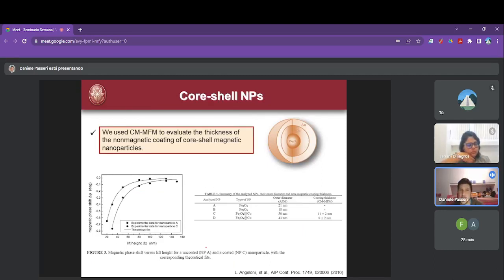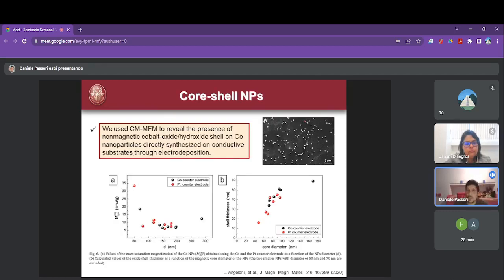Another application: we tried to measure the thickness of the shell of core-shell nanoparticles, so a magnetic core and a non-magnetic shell. And we measured indirectly, of course, the shell of magnetic nanoparticles. For instance, in this case, we had these nanoparticles of cobalt, which were directly synthesized on the substrate, so we couldn't remove them. And we measured the value of the magnetization and also the thickness of the non-magnetic shell. The non-magnetic shell is due to the formation of cobalt oxide or cobalt hydroxide.